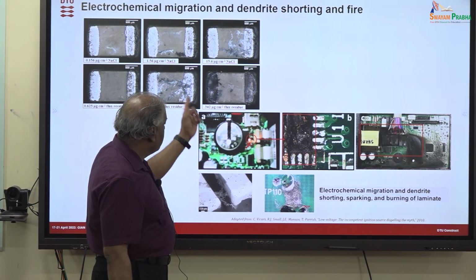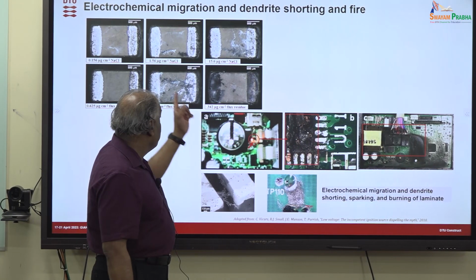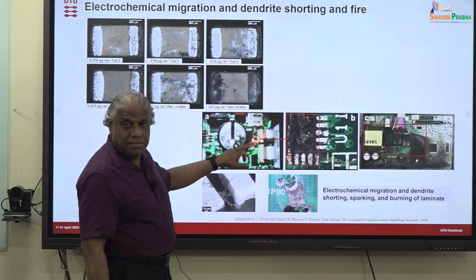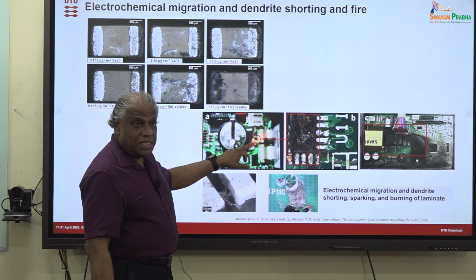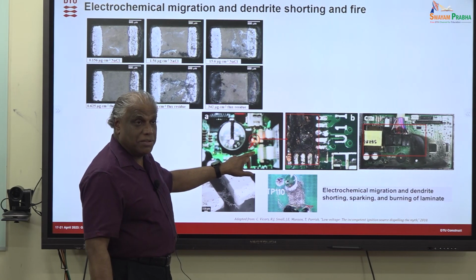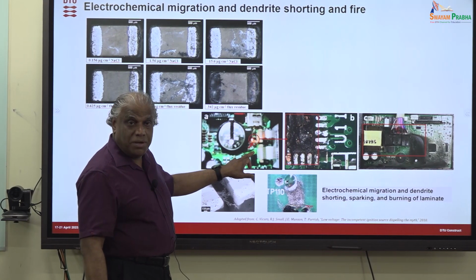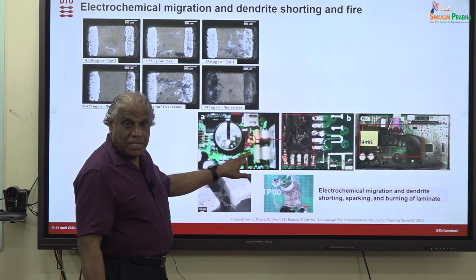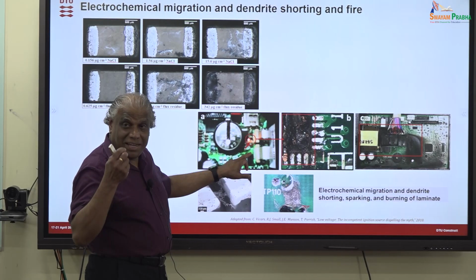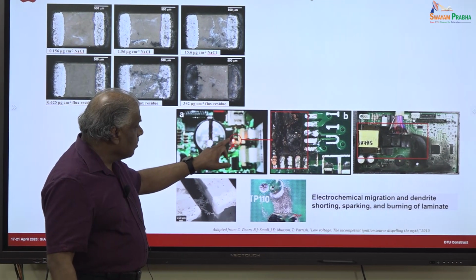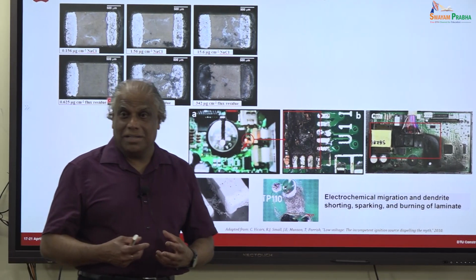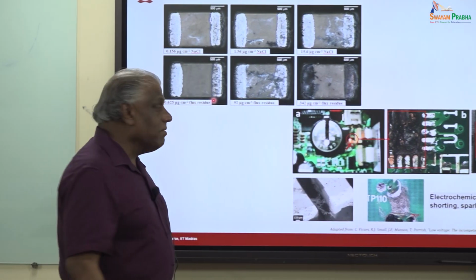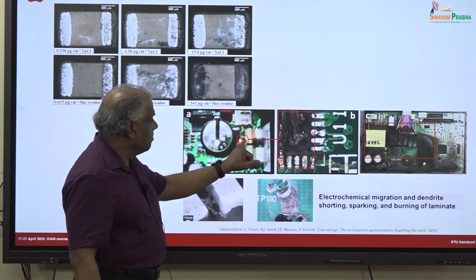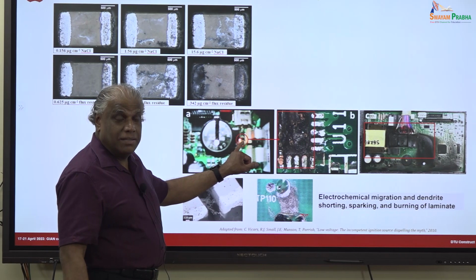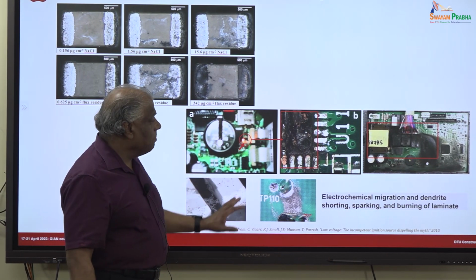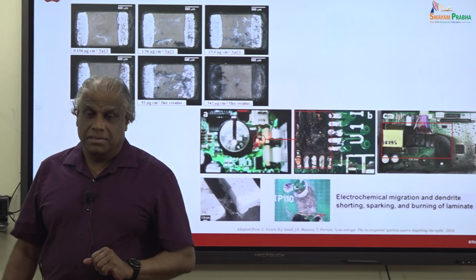If this is happening on a PCB surface, each time it burns, it creates a small spark depending on the voltage. That small spark will burn the polymer, because this base PCB, the green stuff, is a polymer, a glass epoxy composite. It will burn a little bit and create a little bit of carbon. This carbon will start depositing here, and deposited carbon is a very high resistor. Slowly you form a very high resistance between two conduction lines because of the carbon deposition. It becomes red hot and the PCB catches fire. So that's the end result.